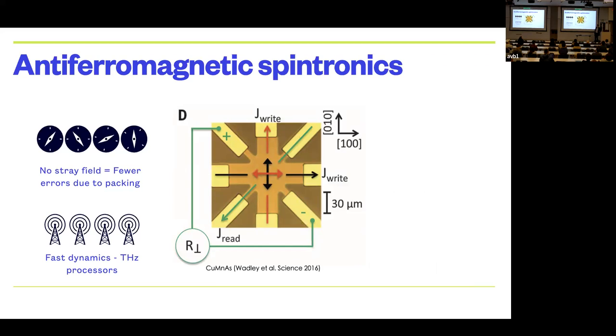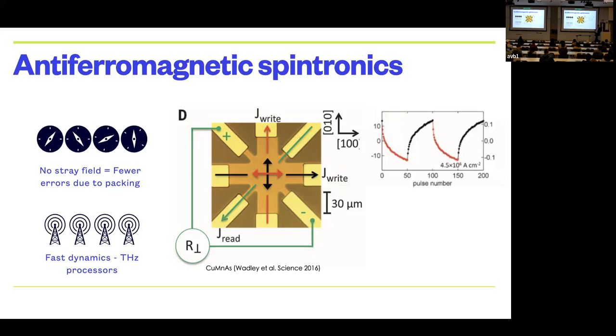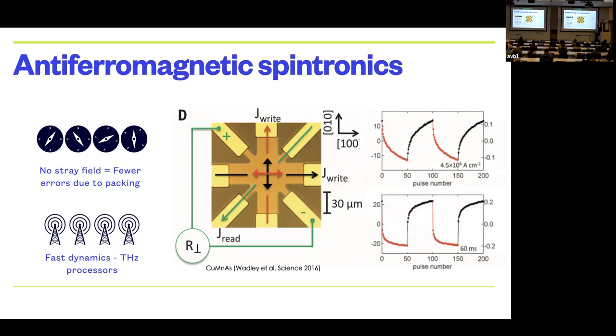The way people use antiferromagnets is in the following way. Here you've got a picture of an actual thin film antiferromagnet, and they've made a little device out of this with 8 contacts. And what they do is pulse electrical current in one direction and electrical current in another direction, and they measure the resistance. Pulsing along the black direction, you get increases in electrical resistance. Pulsing in the red direction, you get decreases in electrical resistance. It's basically like a transistor, right? 0 and 1, 0 and 1. You can switch it. That's the idea. Okay. What does this have to do with anything?